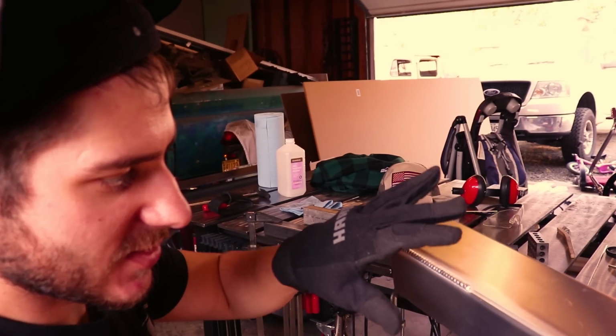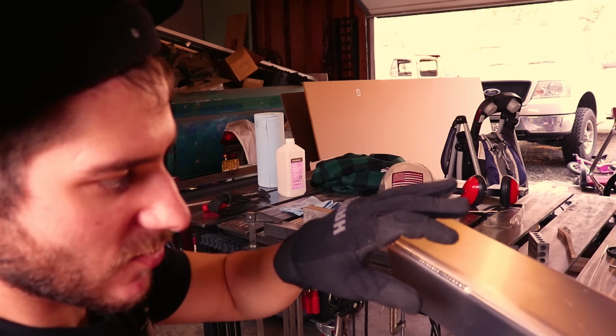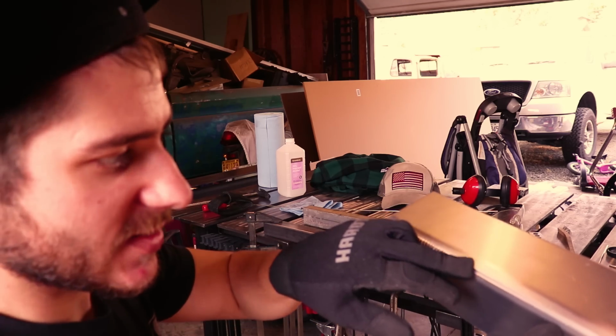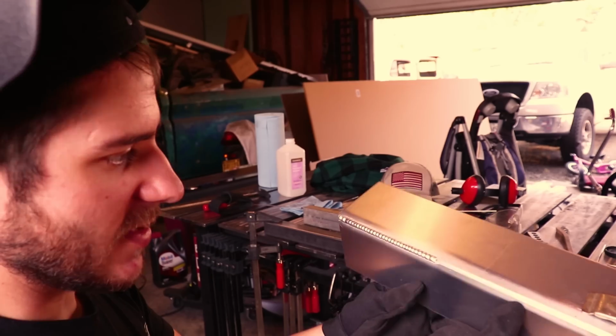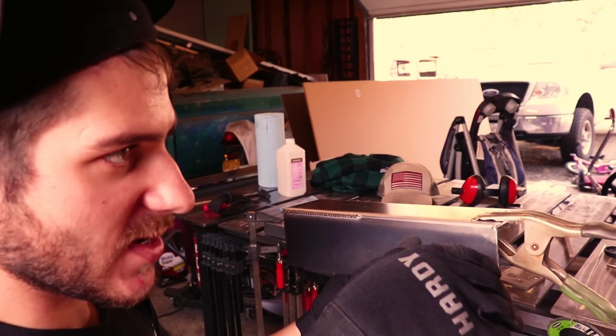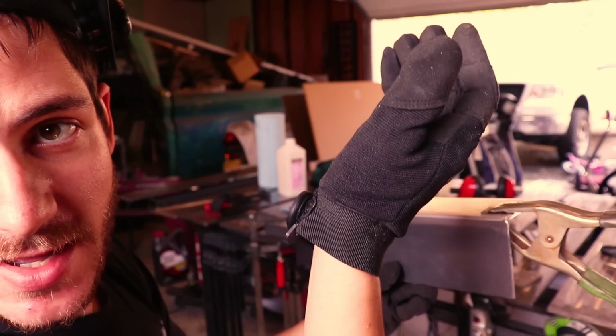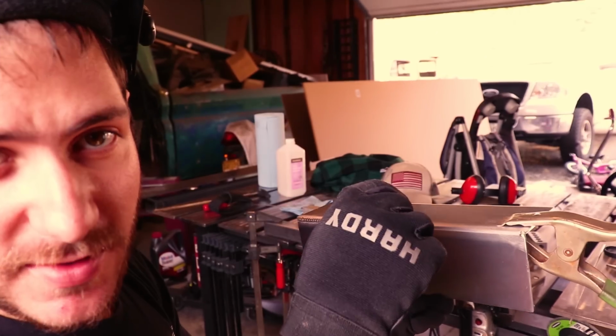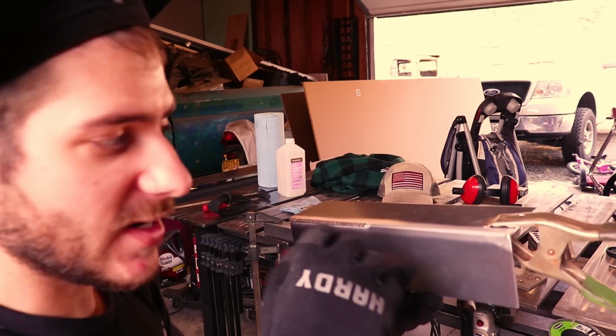You'll see it just kind of like in the reflection just go and kind of sink. And that's when I know that I can start moving and dabbing. And then the whole time I'm going to be keeping it to where I can see it drop when I move forward, and then I add filler and it pushes it back up. If you start adding filler and it just stays sunken, you're too hot. You gotta back off the pedal until it's right at that verge.